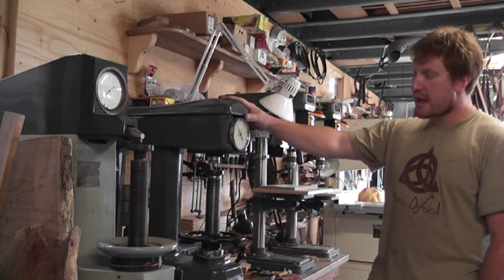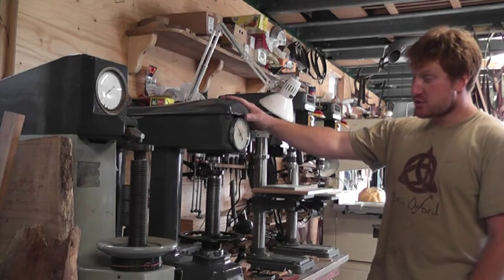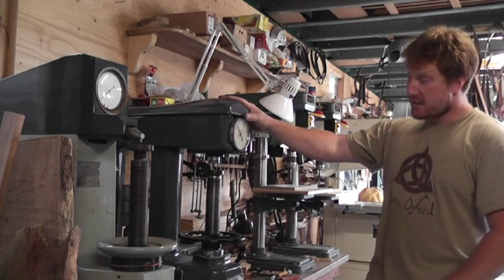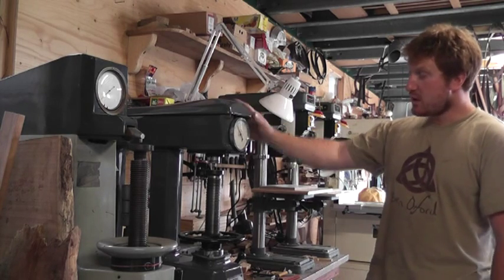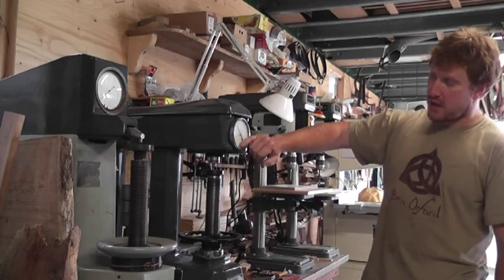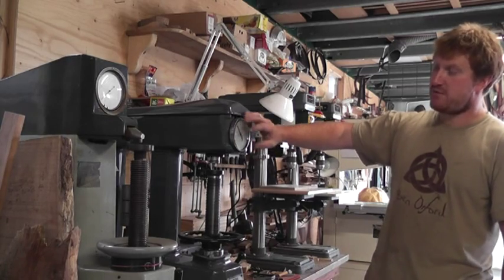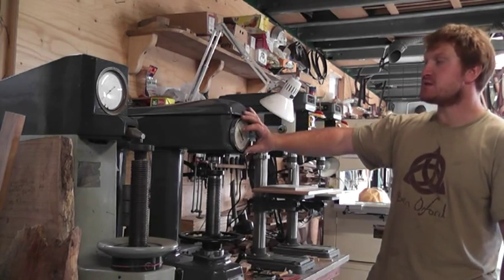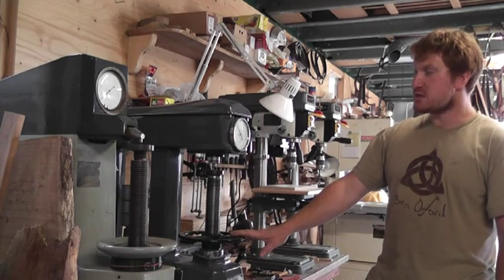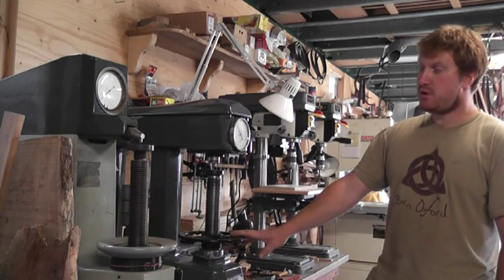I test all my blades after hardening to ensure that I've reached full hardness, and then after the heat treatment cycle I check them again to make sure that I've got anywhere between about 57 and 59 Rockwell C. That's a good general hardness so that it's hard enough to hold a good edge, but it's not going to be too brittle.